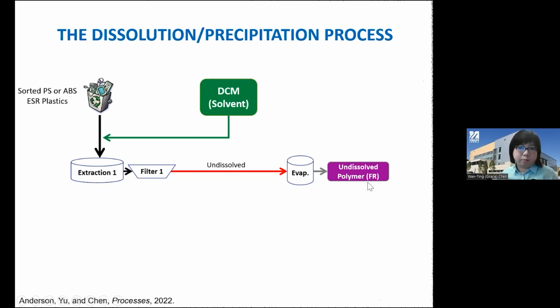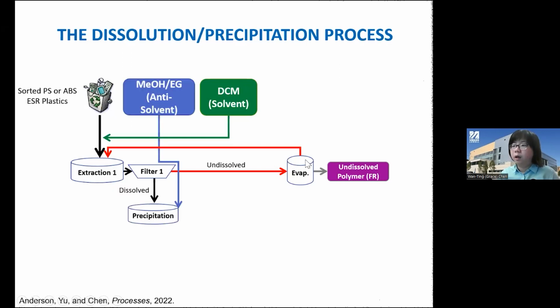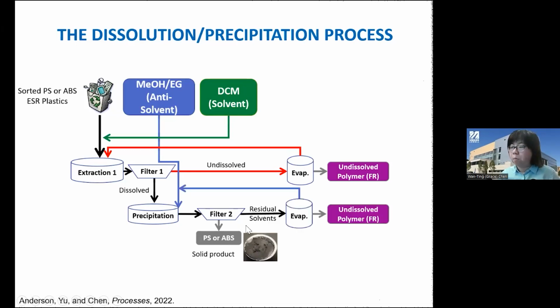In that case, we have polymer that is undissolved and contains a hazardous additive called flame retardants. And then we add another anti-solvent and try to recover the polymer that's dissolved in the solution. In this case, it's methanol or ethylene glycol, or EG. And after that, we filter again, recover the polystyrene family back, and then we'll be able to recycle.